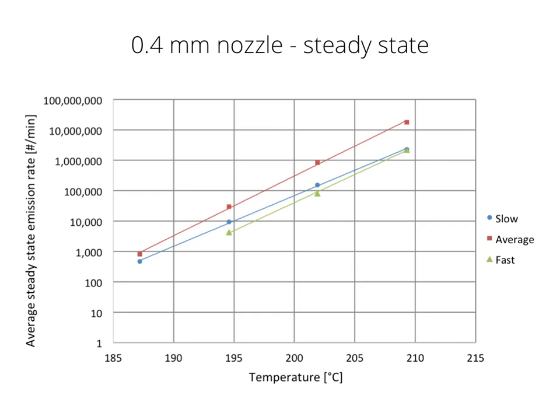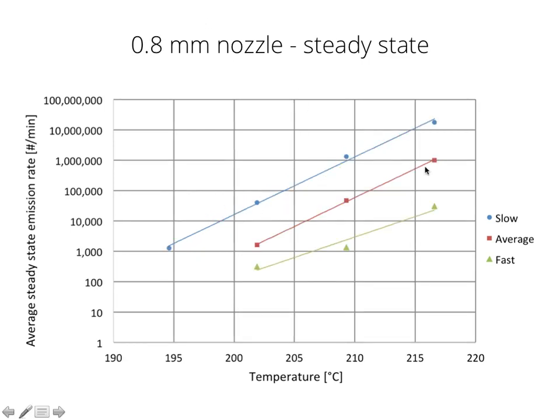So this is actually the interesting finding in my bachelor thesis. And also that these exponential functions actually depict the measured points here quite well. Each dot here, by the way, was run 3 times and then an average was taken. For the 0.8 millimeter nozzle, you can see the slowest printing speed is our highest particle emitter, while the fastest printing speed is the lowest particle emitter.